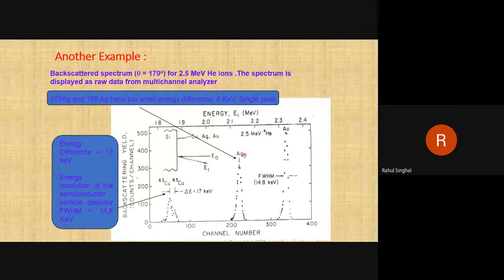But in case of silver, when they collide with silver 107 and silver 109, the energy difference is 6 keV, which is less than the energy resolution of the detector. So in silver, we are not able to see two peaks, whereas in copper, we are able to see two peaks. I'm trying to say it depends on the mass of the elements also. For the two isotopes of copper, the difference in mass number is 2, like here 63, 65. Here also 107, 109, the difference is 2. But for the copper, we are able to see two masses. For the silver, we are not able to see two peaks.